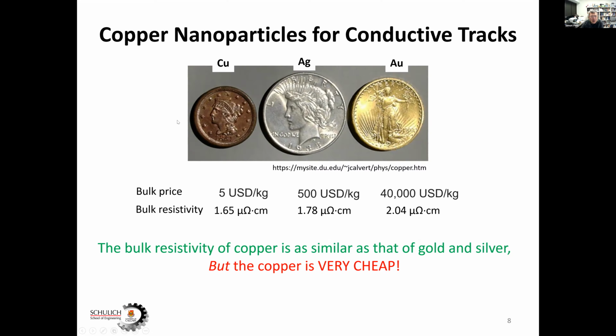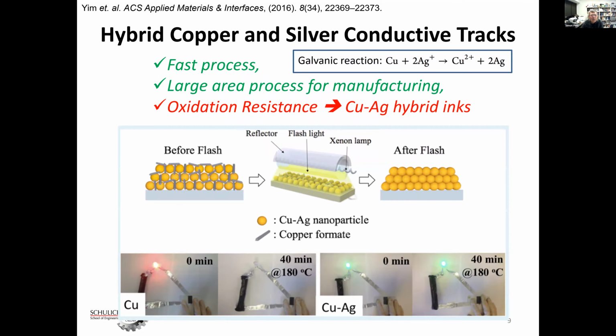And people may ask, why not use copper for the circuit tracks and whatnot? They're very cheap, yet you have good electrical resistivity. Well, the problem is known as oxidation. When you make copper, coppers can get easily oxidized. So we spent many years trying to solve this thing. And there we came up with a special formula. We call this a recipe. We call this a hybrid copper and silver. So we mix copper with the silver salt, and through flashlight, we can make fairly decent copper tracks.